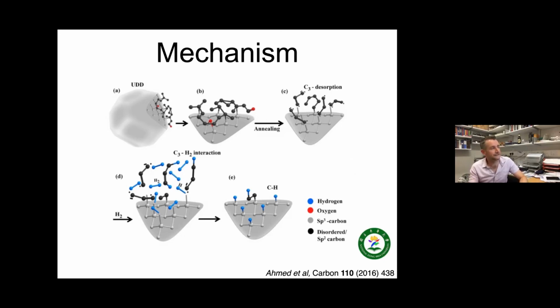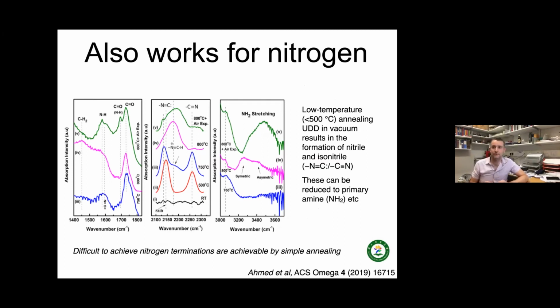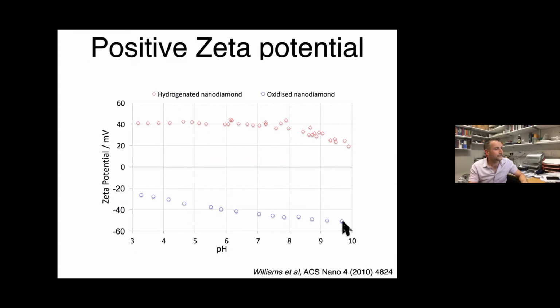But a consequence of that is that it also works for nitrogen. You can play the same game. If you take these detonation materials and you heat them up in molecular hydrogen, sorry, nitrogen, excuse me, you can get all sorts of weird amine terminations that are actually normally quite difficult to make. So I think this is quite an interesting and underappreciated paper, also from the Dongwha group. This is a bit surprising.